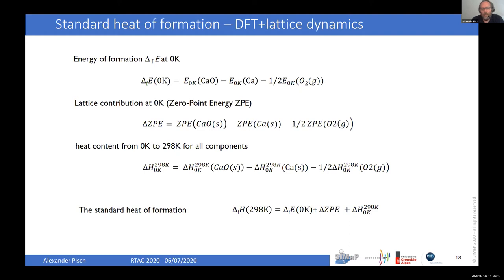And then because I have a lattice contribution even at 0 K, the so-called zero point energy, I have to do the same with the calculated zero point energies that I got from the lattice calculations. And then as I have the Cp from zero to room temperature, I can calculate the delta H from 0 to 298, which is just the heat content of, in this case, lime, calcium, and oxygen gas. And if I sum up all three contributions, I get the heat of formation, and the heats of formation I will present later in this talk are all calculated in this way.